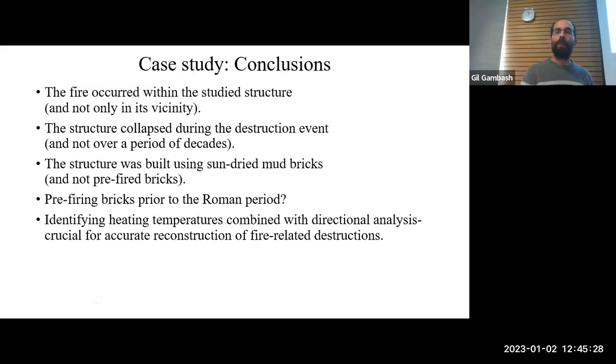The structure collapsed during the destruction event, at least the area that we sampled, because the collapsed materials also recorded the magnetic field after their collapse, more or less in the position in which we measured them, and not over a period of decades, as was suggested before. And the structure was built using sun-dried bricks, not pre-fired bricks, as was suggested.